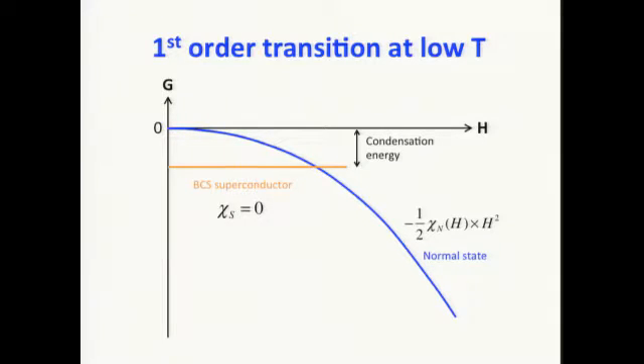It can be seen by plotting the free energy versus the magnetic field in the zero temperature limit. The blue line here is the normal state metal, which has a paramagnetic energy of -1/2 times the spin susceptibility times h squared. A BCS superconductor does not respond to a magnetic field, so the spin susceptibility is 0. Ignoring orbital effects, you only have the condensation energy, which stays constant with the external magnetic field. The touching point here defines H_P, the Pauli paramagnetic limit, and you can see that they touch at a kink, which is the definition of a first order phase transition.